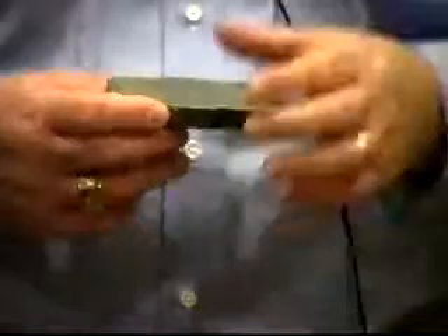You know, I've passed this around a number of times, but this is a cross section of an Electro Slag titanium weld that was made at Oregon Graduate Center on a classified contract in the mid-'80s. And the weld zone ends up, you're melting back some of the base plate. You can actually see the mold on here of the copper chill blocks on either side, and you're basically making a casting going straight up.